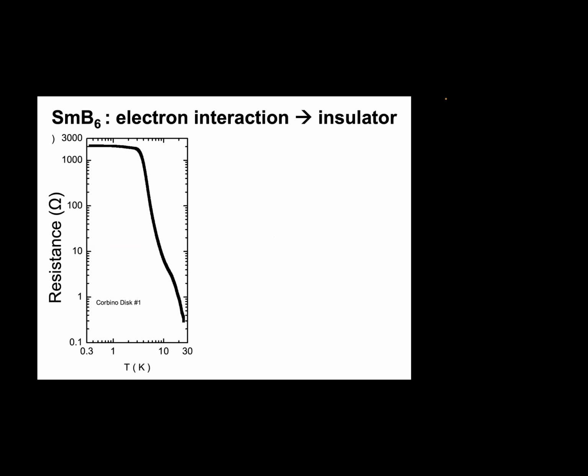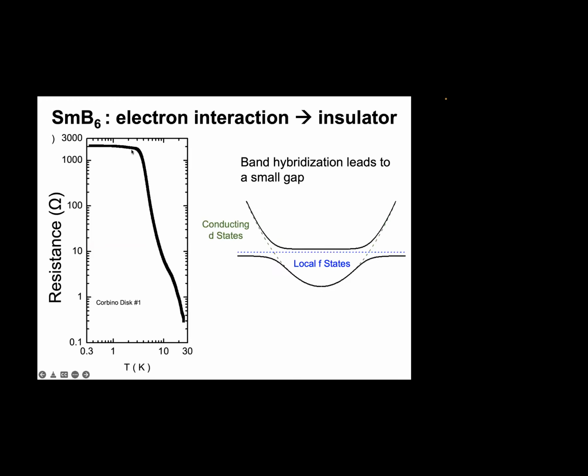Now you see the saturation clearly from 20 or 30 Kelvin to base temperature. There are about 3 or 4 orders of magnitude change of resistivity, and then it stops changing. So this activation suggests we have a small gap.